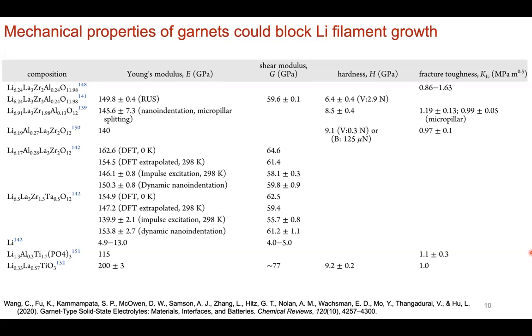And thus, when you do the characterization, these filaments kind of look mossy. So sometimes you'll see that terminology in the literature as well: mossy growth, filament growth, dendritic growth. All of those terms more or less convey the same message, which is that redeposited lithium metal is not being deposited uniformly. And of course, your filament is growing and then eventually shorting. It all conveys the same message, but the technical term I try to distinguish, because dendritic growth means something else in the materials science definition.